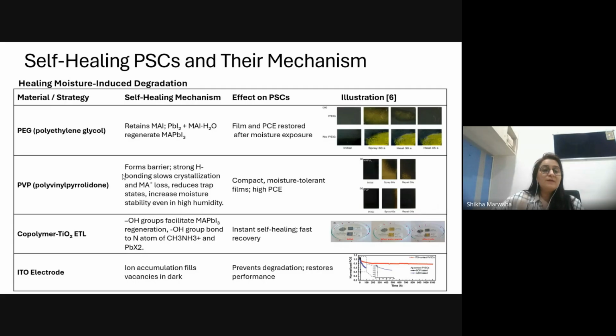Why? Because this PVP, when it was used with the perovskite, basically formed a barrier against the moisture or against the H2O. The H bonding that it formed actually slowed down the crystallization of methyl ammonium, and it also reduced its trap states. So thus, stability against moisture and humidity has been increased.